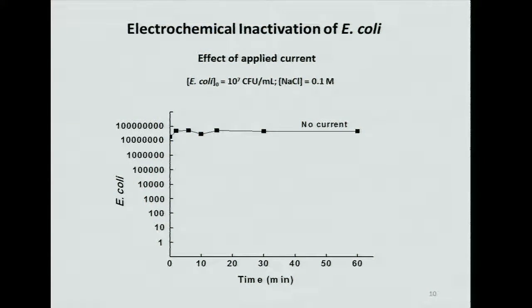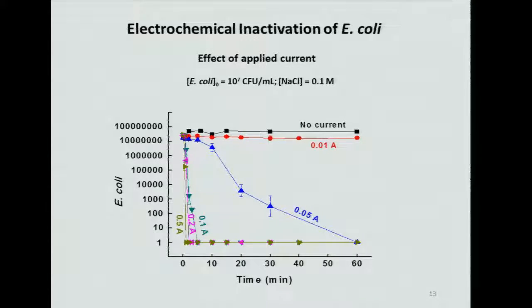So we tested the effectiveness of our selected coating composition for the inactivation of a test microorganism, which was, in our case, non-pathogenic E. coli. When there was no current passing through the electrochemical cell, no change in the concentration of E. coli was observed after 60 minutes. When there was a small amount of current passing through the cell, there was a small decrease in concentration of E. coli after 60 minutes. By further increasing the current, up to 0.5 amp, there was almost instantaneously complete inactivation of E. coli in about 30 seconds.